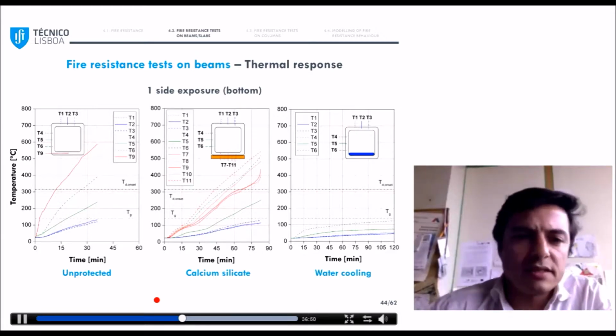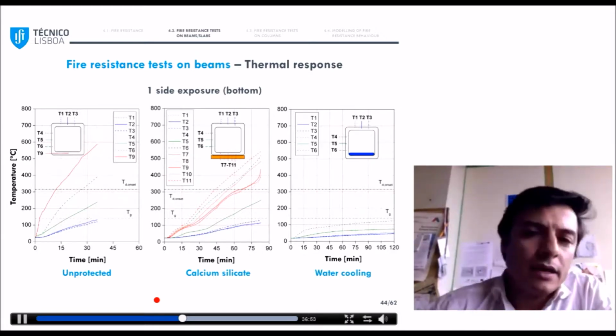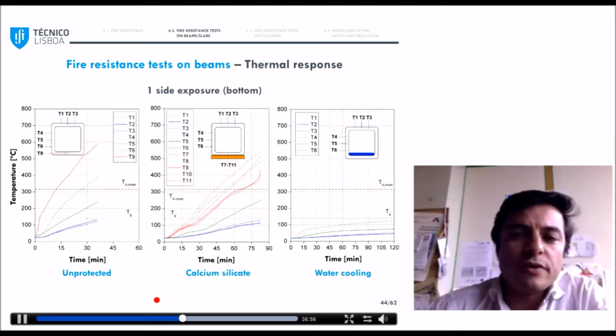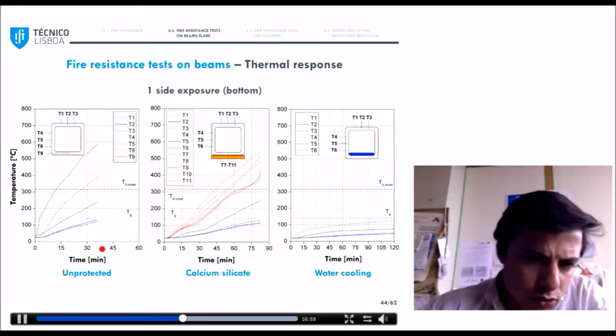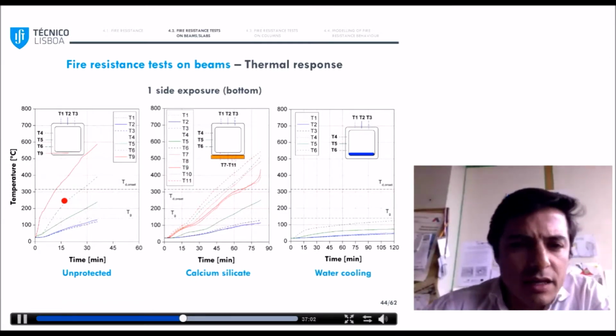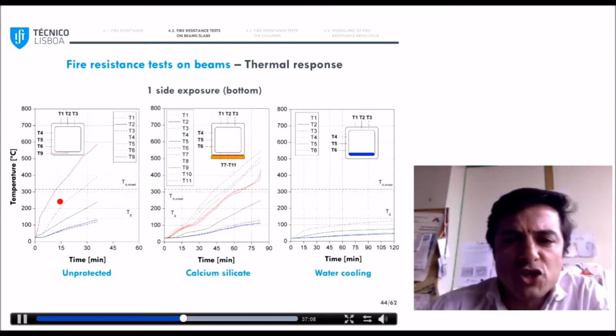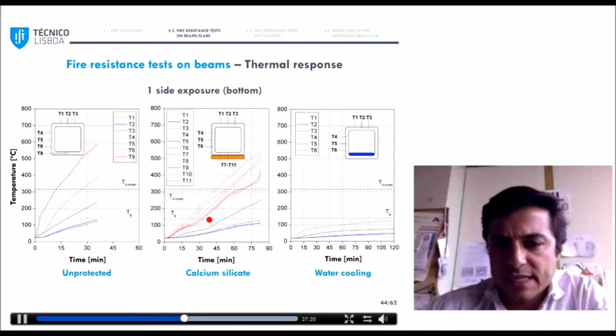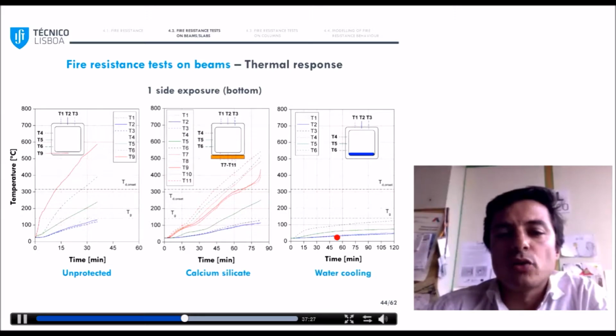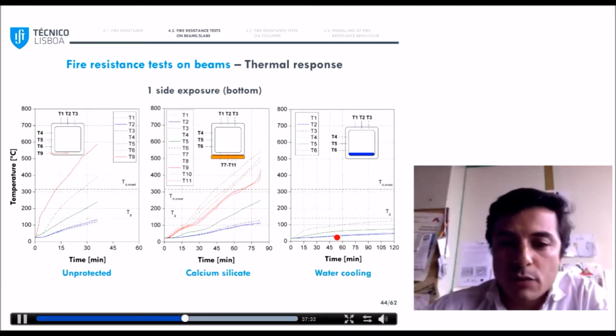So for the thermal responses, just highlights of some of the results we obtained. You can see here the temperatures for different beams under one side exposure. So for the unprotected beam on the left, you can see that the center of the bottom flange, the red curve, attained the decomposition temperature only 10 minutes after the test started, and that the top flange reached the TG at collapse. With calcium silicate protection, as expected, temperatures considerably decreased in all section walls, and with water cooling, temperatures in the webs and top flange were kept below the TG for the 2 hours of testing.